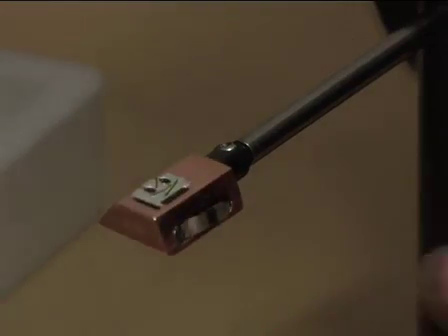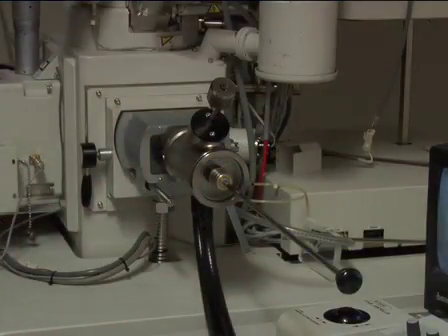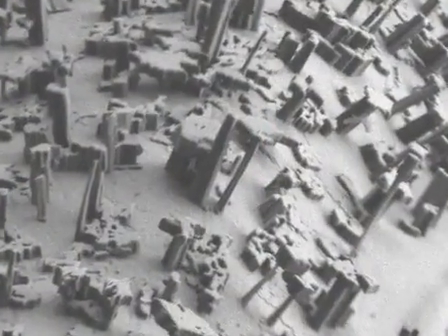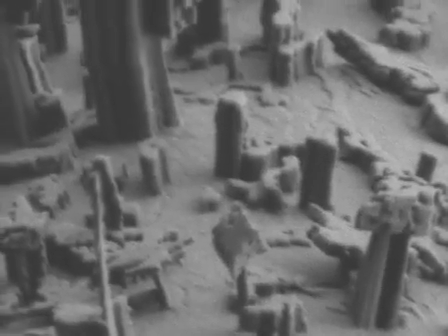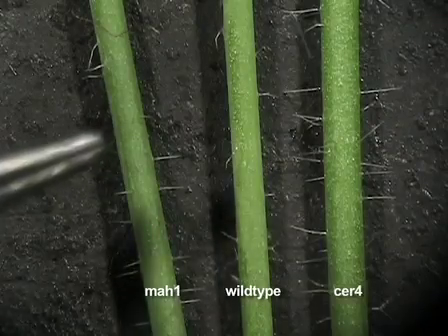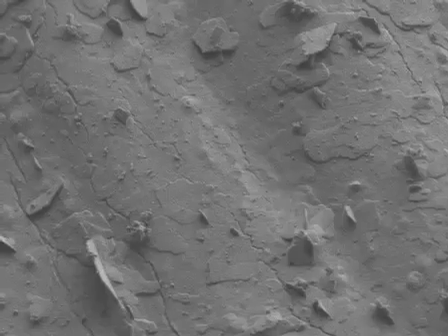When the samples are transferred to the cold stage of the microscope and visualized, you can see that the surface of the wild-type Arabidopsis stem cuticle is covered with crystals. The light scattering from those crystals gives the stem its whitish appearance. Now remember how the stem looked shiny on the mutants. You can see in the SEM images that it lacks the crystals on the surface.